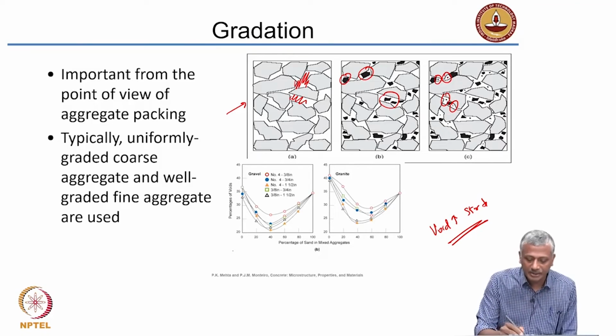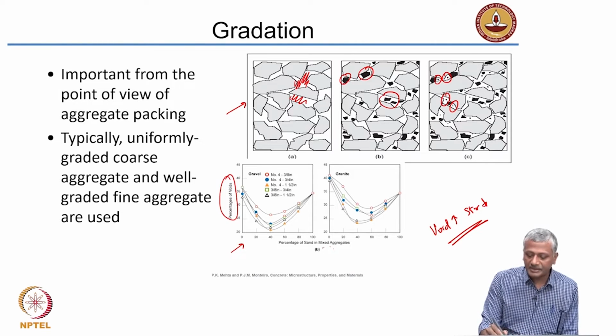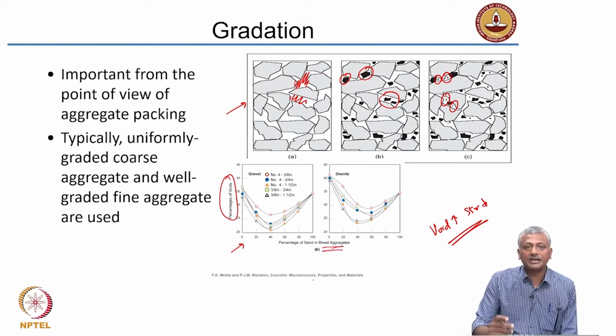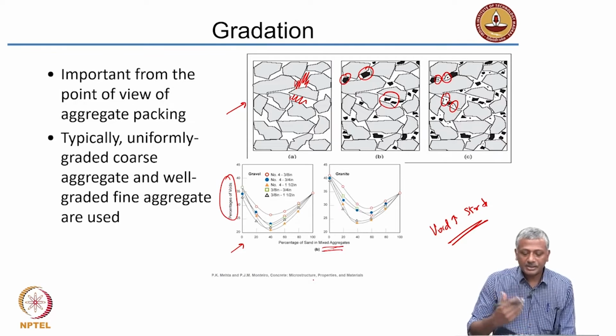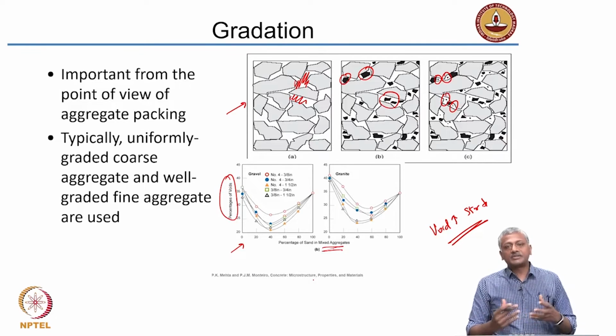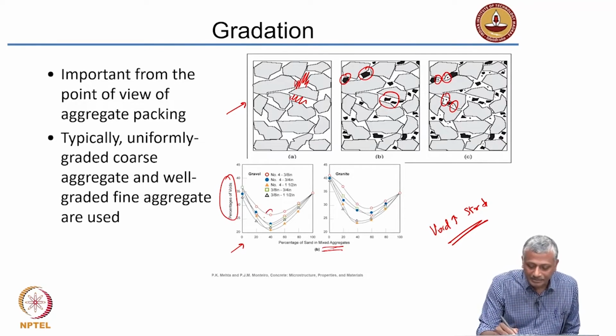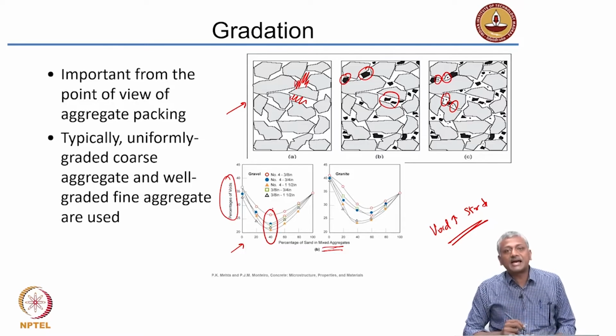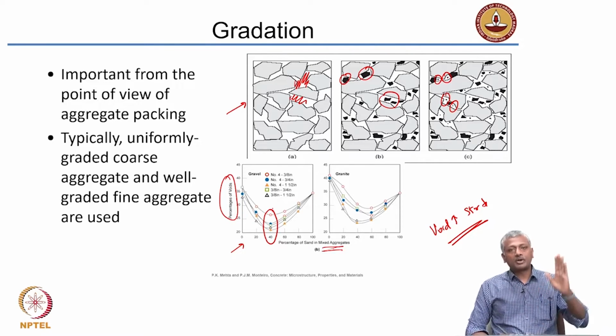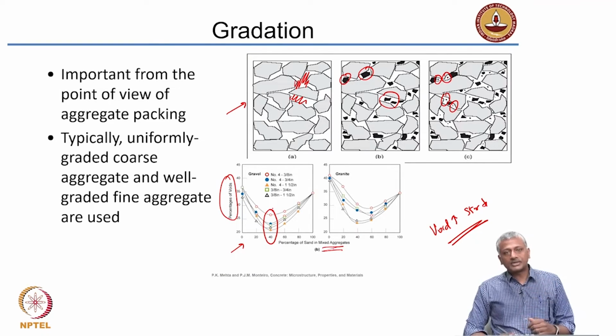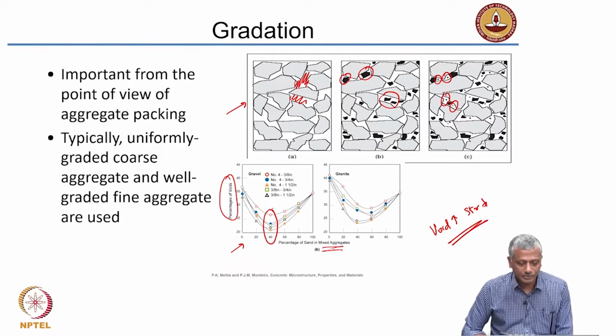So, indeed, if you look at this experiment here, the percentage of voids is plotted on the y-axis and the percentage of sand in mixed aggregate on the x-axis. Okay, they have taken coarse aggregate and sand. They are just mixing the coarse aggregate with sand and finding out that at 40% sand in the mixture, that means 40% sand and 60% coarse aggregate, you get the lowest percentage of voids. Okay, this is quite easily done. Some of you may actually be doing this in your laboratory exercises also.